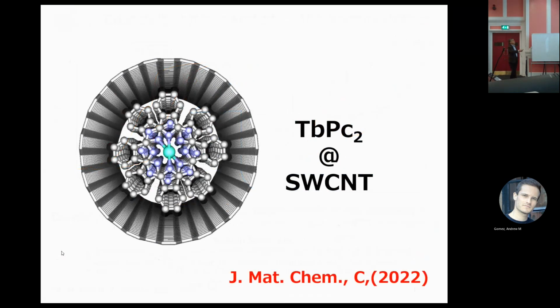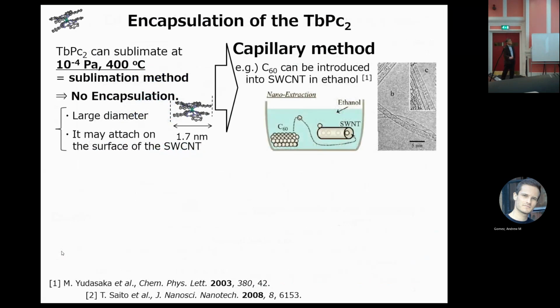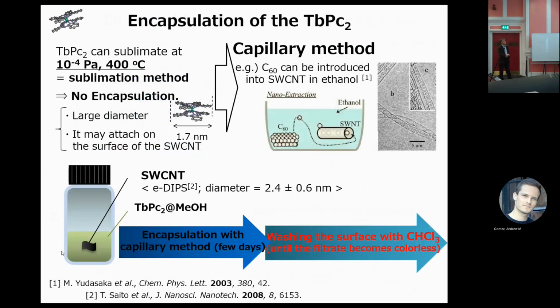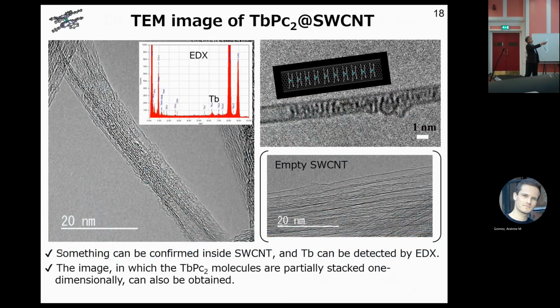So another example, double-decker phthalocyanine terbium, we inserted in the single carbon nanotube. In this case, we use a solution method. A few days and push outside. So you can see this motif, double-decker phthalocyanine is stacking in one dimension. And in the EDX, terbium is included.